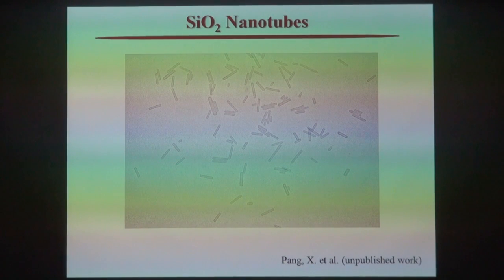And of course, if you can design, as I said, bottle brush like ABA tri-block copolymer, you can sequester the precursors in the intermediate block of the bottle brush like block copolymer, and make them into nanotubes. So this particular case is silicon oxide nanotubes. We know the nanotube structure is quite intriguing. So you can use this, for example, silicon oxide nanotubes. You can convert silicon oxide into silicon and use this nanotubular silicon for lithium-ion battery research to accommodate volume expansion in the system.